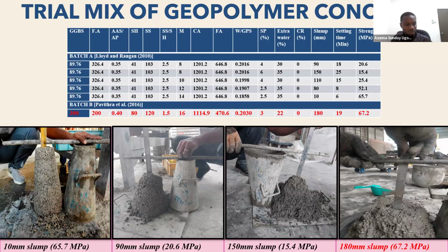And normally, if you go through journals, if you look at the parameters we discussed, the binder content, the ratio of sodium silicate to sodium hydroxide, the molarity and all that, I never discussed extra water. If you read a lot of other journals, you see almost the same thing. They don't discuss extra water. Now, it is almost impossible, 99% impossible, to produce geopolymer concrete without extra water. I don't want to believe that these literatures don't use water; they use it and don't include it in the journals.